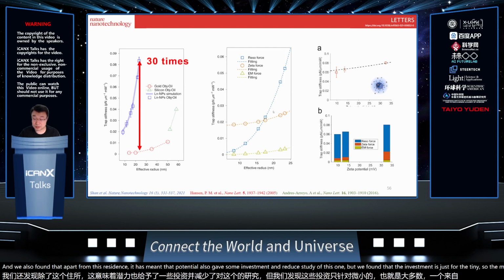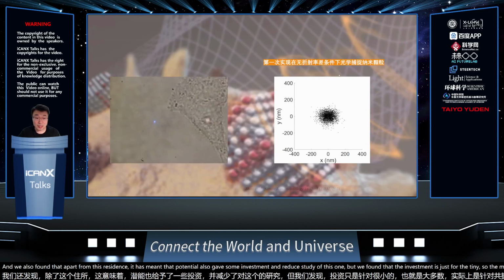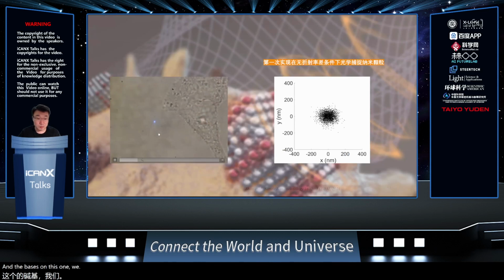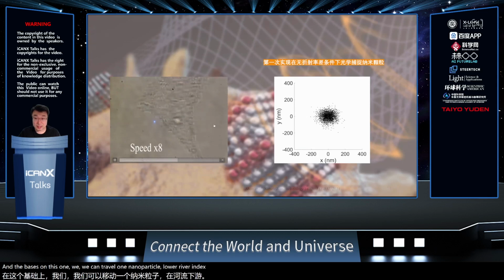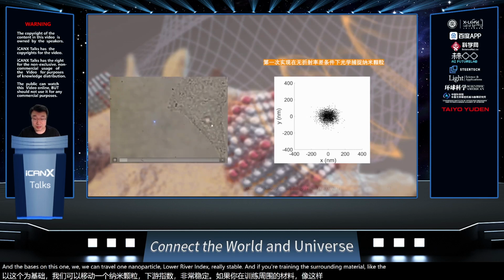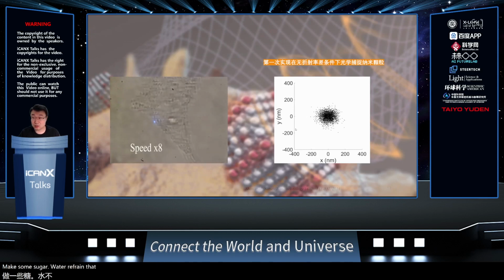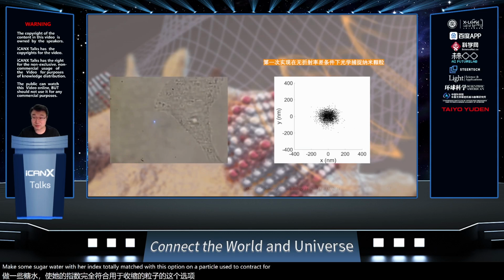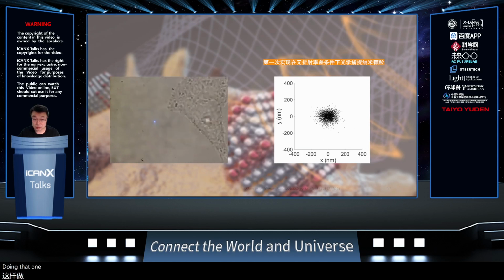We studied this, but found that the enhancement is really tiny. So the majority for larger particles comes from this resonant effect. Based on this, we can trap a low refractive index nanoparticle really stably. And if you tune the surrounding material, like making sugar water whose refractive index totally matches the upconversion nanoparticle, you can still trap it. This is the first time doing that.